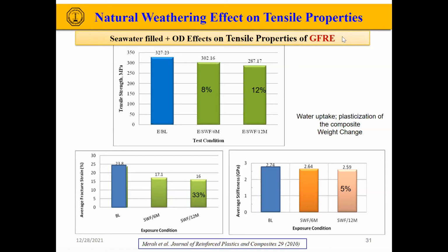Okay, so this is the natural weathering effect on tensile properties of glass fiber reinforced epoxy. What you see here, the blue bar is the epoxy baseline as we received it. That's the average tensile strength. We usually test 3 to 6 specimens for all these. It took us 5 years and maybe 2 or 3 months to finish all these exposures and testing. So it is about 327 MPa.